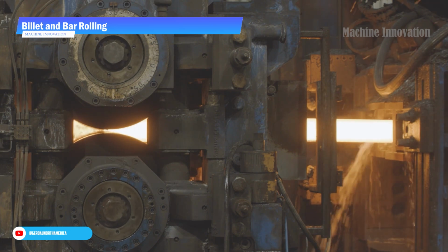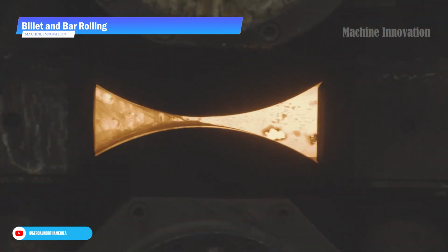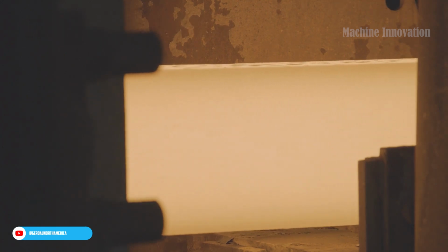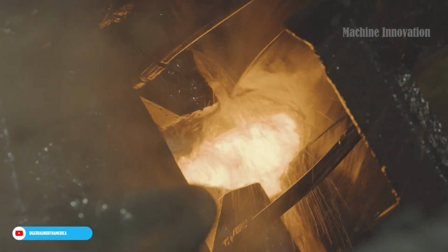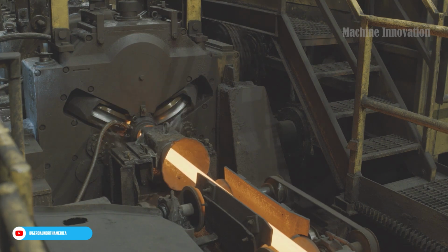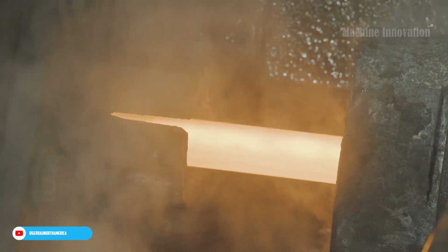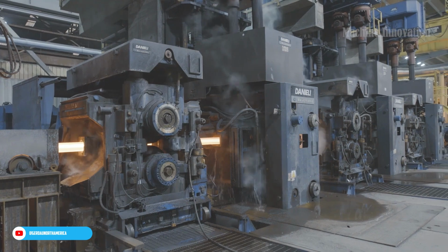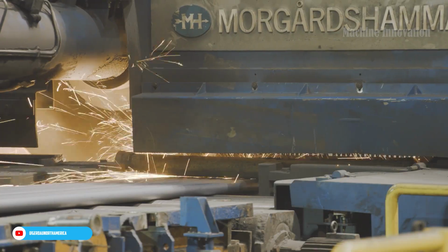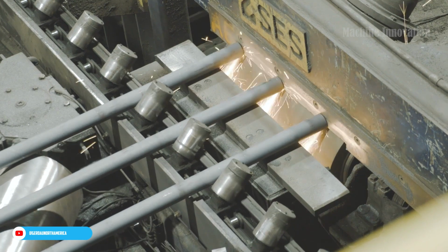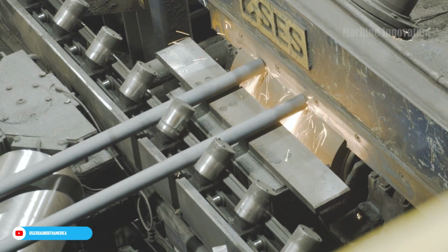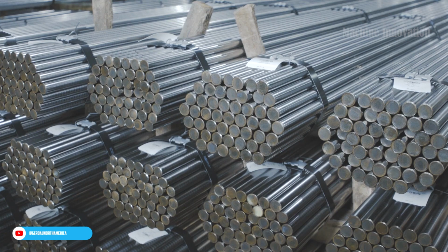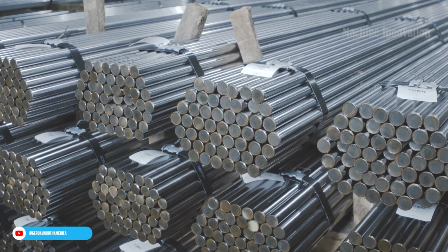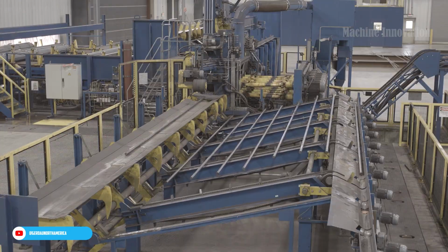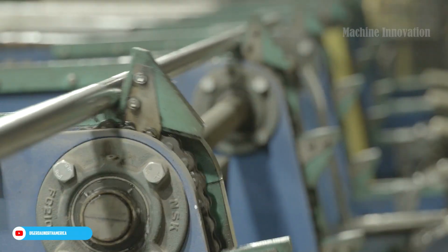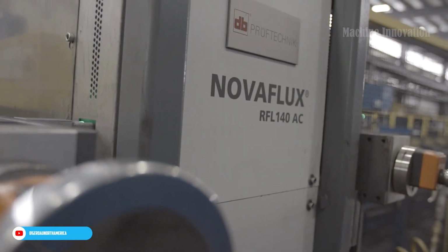Once solidified, the billets move to Gerdau's rolling mills. Here, they're reheated to the optimal temperature for shaping. Any scale formed on the surface during heating is removed before rolling, ensuring the steel's surface remains smooth and clean. Gerdau's precision rolling mills can produce bars of varying diameters, from as small as 5/8 of an inch to 6 inches, with tight size tolerances. This precision is essential, as it allows Gerdau to meet the specific needs of industries that demand high-quality steel components. Each bar's length is controlled using hot saws, and larger bars can be automatically chamfered to further refine the final product.